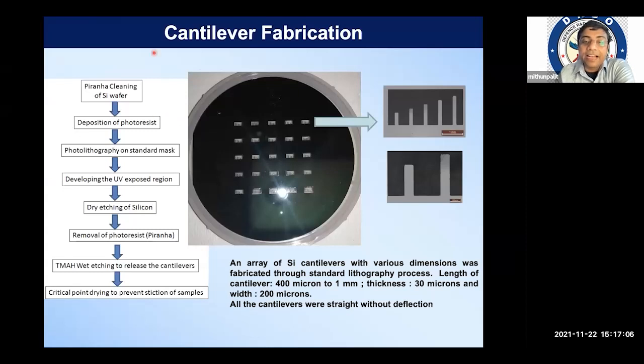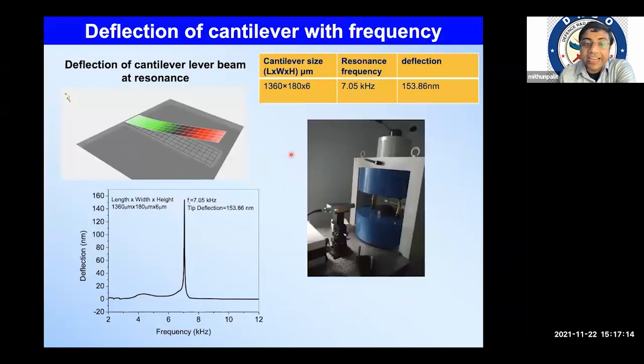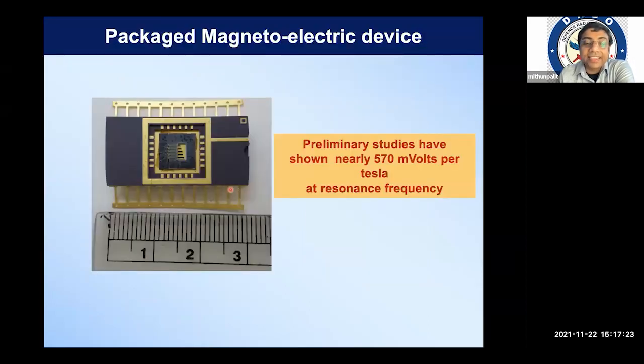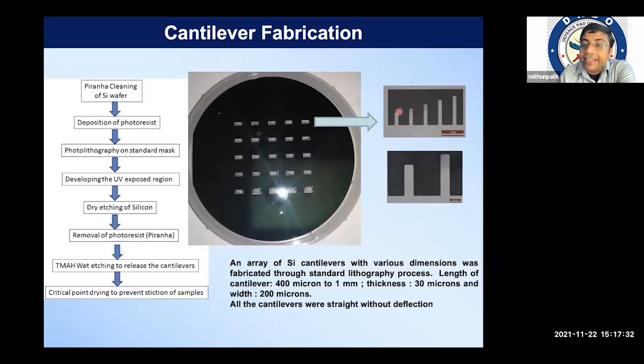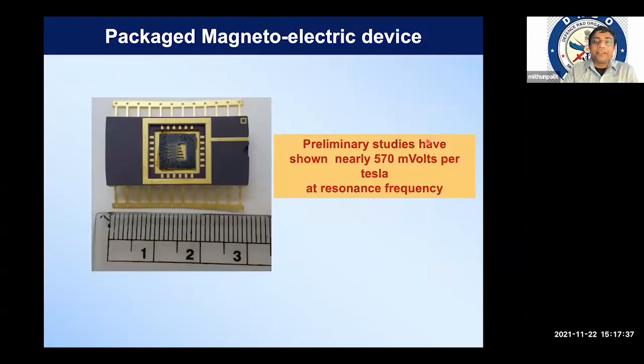So IIT Pilani has a facility for micromachining of silicon. So they have produced such nice small cantilevers from a silicon wafer. And then we in DMRL have grown the iron gallium thin film over it, and then we have produced the cantilever devices. And this is the package, and you can see that there are different lengths of cantilever. So each length of cantilever has a different resonance frequency. Therefore, it can sense the AC magnetic field of different frequency. So basically, we have produced a wide band AC magnetic field sensor.